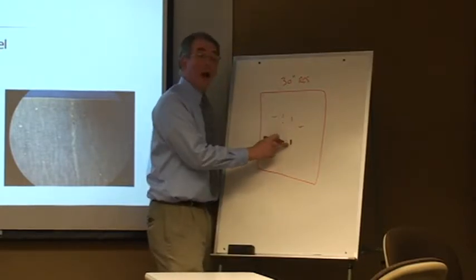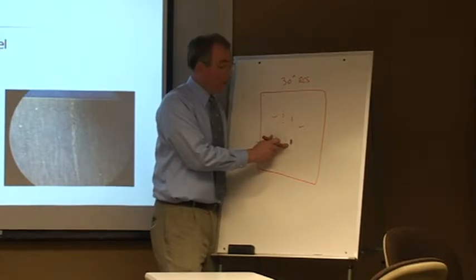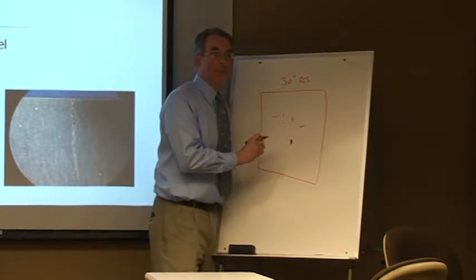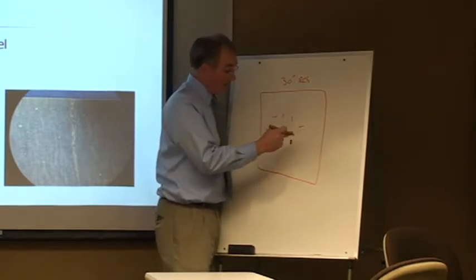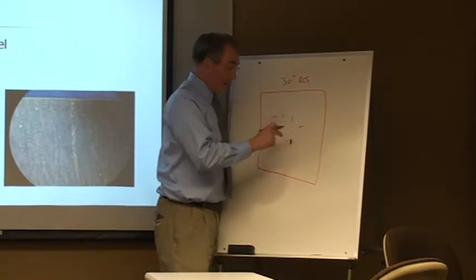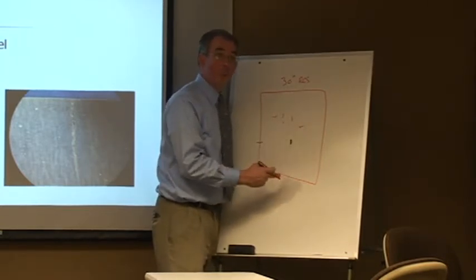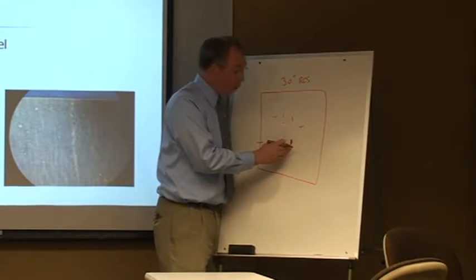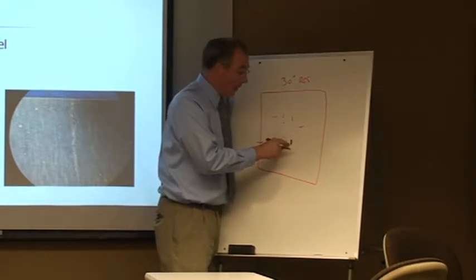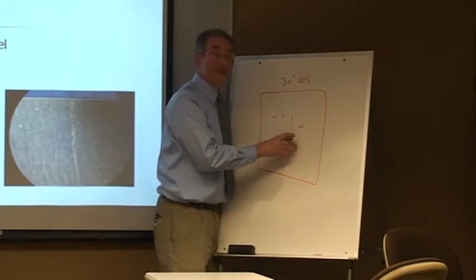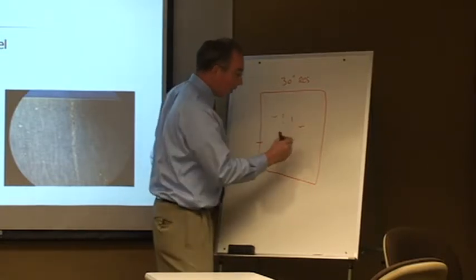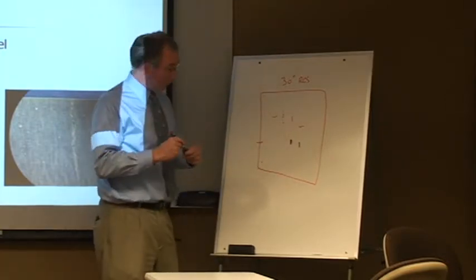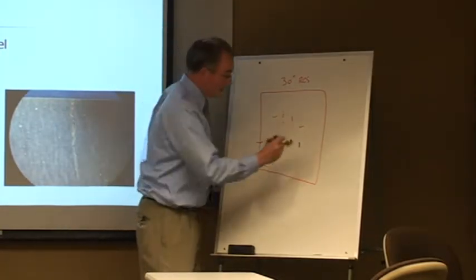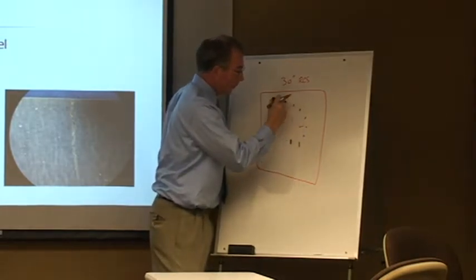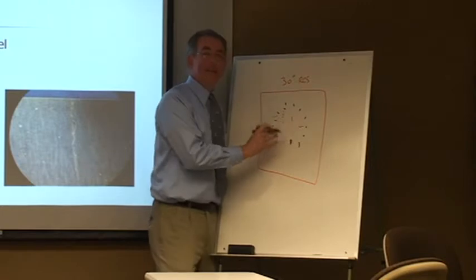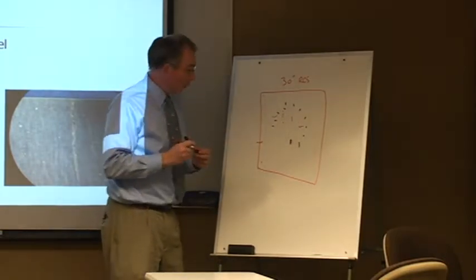Okay? The more hydrogen that accumulates at this area is going to create stress. The higher the stress, and it's a function of the steel grade and the strength of the matrix as well, the higher the stress is, you can actually get to the point where the stress created by this hydrogen exceeds the strength of the matrix. And what you end up with is a crack. And, in many cases, several cracks. And that's a defect called hydrogen flake. That's what we want to avoid.